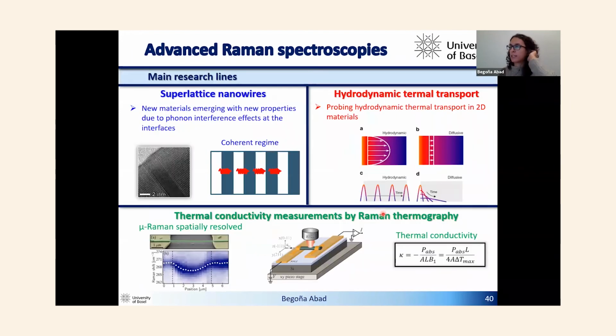So with this setup, we will be looking at superlattice nanowires, which are new materials with new properties arising from interference effects at the superlattices. We will also probe hydrodynamic thermal transport in the materials. And not only with this setup, but just with conventional Raman, we are doing thermal conductivity measurements by Raman thermography, where we are able to probe the temperature profile of a suspended nanowire, and applying a thermal model, we are able to extract the thermal conductivity of different nanowires.